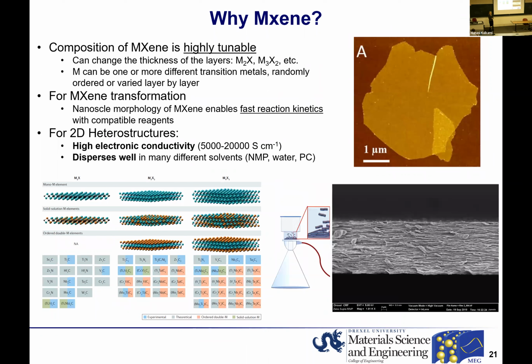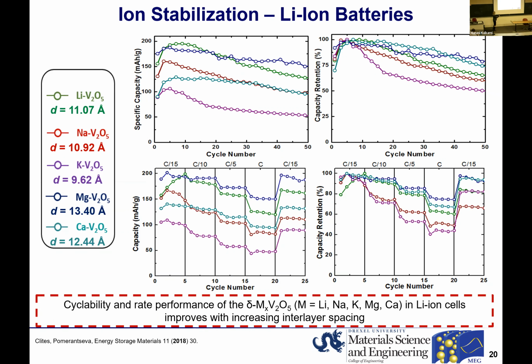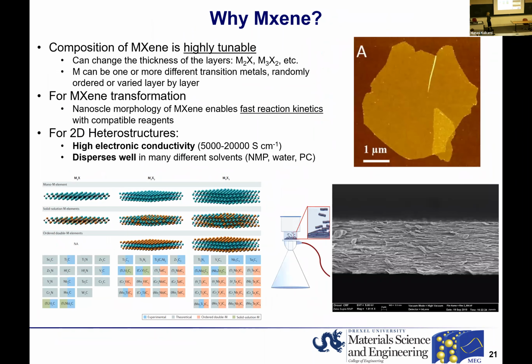But the question is, can we improve the performance of these materials further? Because even for magnesium pre-intercalated V2O5, there is still some obvious capacity decay after 50 cycles. So this is still not so good for a battery, right? For the real battery that one wants to use to power a smartphone. So with this kind of goal to improve the electrochemistry further, we started looking into alternative precursors in our synthesis.